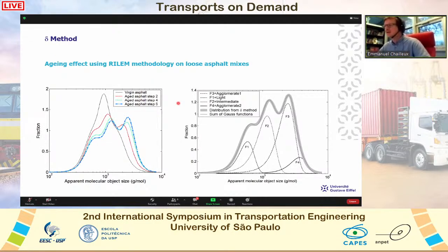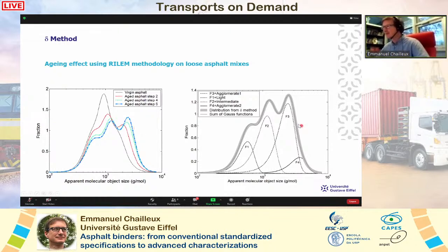The other example is what happens during aging. And here we have extracted asphalt from a loose mix, which was aged during several steps at different temperatures. And you see here from the virgin asphalt, from the aged asphalt, step by step, we have more and more very heavy molecules. And each time we see this effect that we create more and more heavy molecules after aging. We can find 4 populations in this type of curve. Here you can model this distribution using F1, F2, F3, and F4 populations,